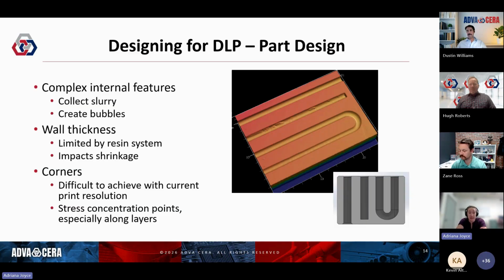If we're working with a part that is a consistent thin wall, we've got lattice cubes that have 150 micron struts, and the whole part is about 1 centimeter across. Because all of the walls are consistently thin, we can do 150 micron walls with, I think they're about 200 micron wide channels, because the whole thing is very thin and debinds really evenly. But if you wanted to take a 4 millimeter wall base of the part and add a 0.5 millimeter thin wall on top of that, you would have some difficulties unless it was dramatically transitioned from that thick to that thin section. So that's where the feature dependence comes in: we can make the really small stuff, but the rest of the part has to be able to accommodate it during the processing. Does that help with that question?